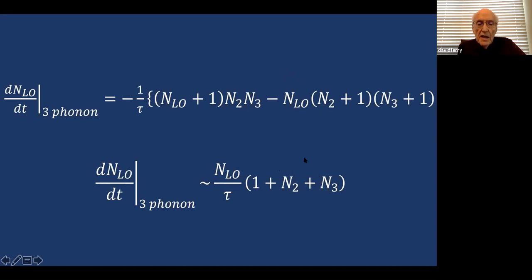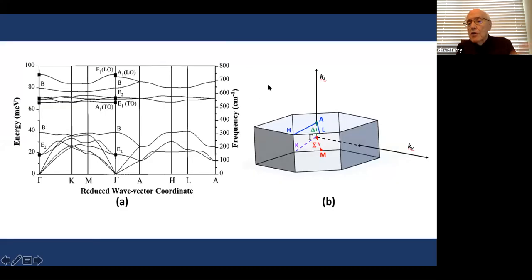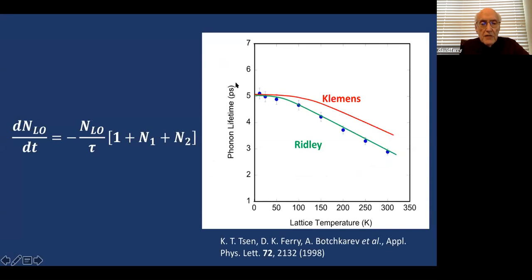And that's the key. So the data that we want to show you is taken on gallium nitride and its wurtzite. Okay, this is the wurtzite unit cell. Now the thing about that is you have A1 and E1 LO modes. One of these is in the basal plane of the wurtzite, and the other is perpendicular to it. Okay, but the electrons interact with both of them. So they both get driven out of equilibrium. Now you see here that from LO there's a big gap down to the acoustic, so you could actually cut off the Klemens mode, right? And so we would expect to see Ridley dominate, and in fact, that's what happens.